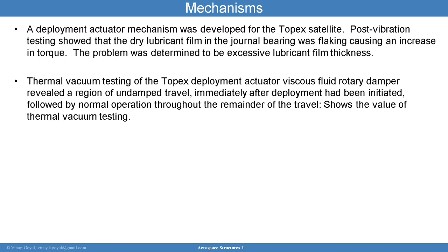of them was developed for the TOPEX satellite, and post-vibration testing showed that the dry lubricant film in the journal bearing was flaking, causing an increase in torque. The problem was determined to be excessive lubricant film thickness. Thermal vacuum testing of the TOPEX deployment actuator, viscous fluid rotary damper, revealed a region of undamped travel immediately after deployment had been initiated, followed by normal operation throughout the remainder of the travel. It showed the value of the thermal vacuum testing. It showed that when you do that, it can reveal issues with the design.